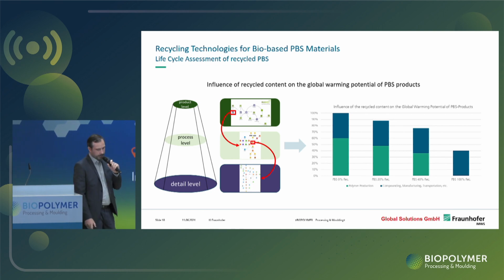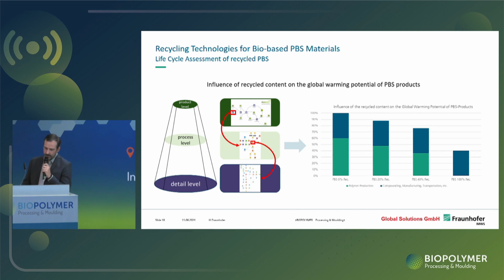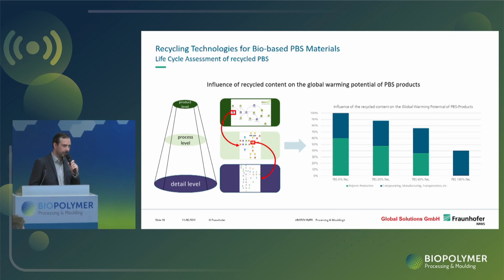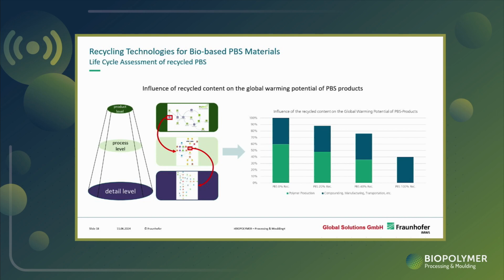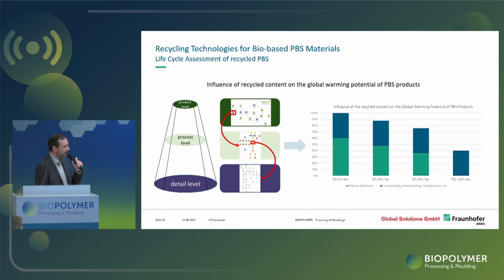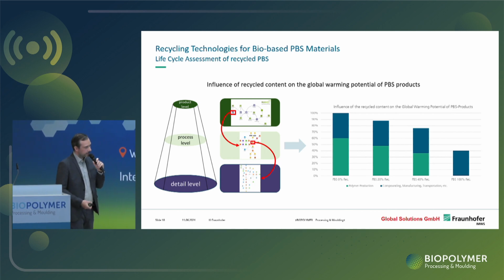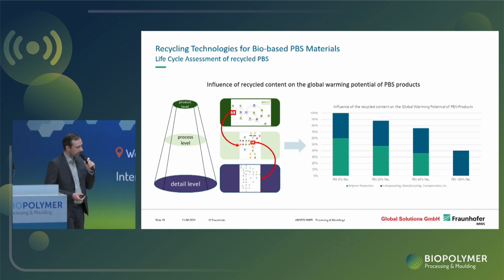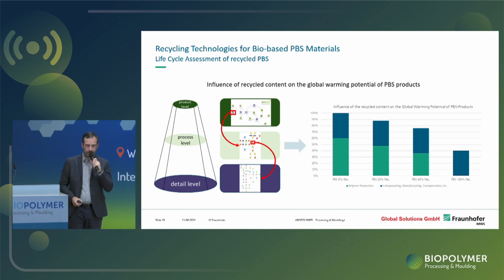Good. So in our project, we also looked into the life cycle assessment. Is it really beneficial in terms of carbon footprint to use recycled material? Here you can see that we have analyzed the complete value chain of the production of PBS. This would be the product level on top in the green box, and then you can separate these different processes into sub-processes, and those again into specific processes. All of these boxes have their own input and output, and at the end you can calculate the carbon footprint of your product. For bio-based PBS, 60% of the carbon footprint is produced to make the polymer.